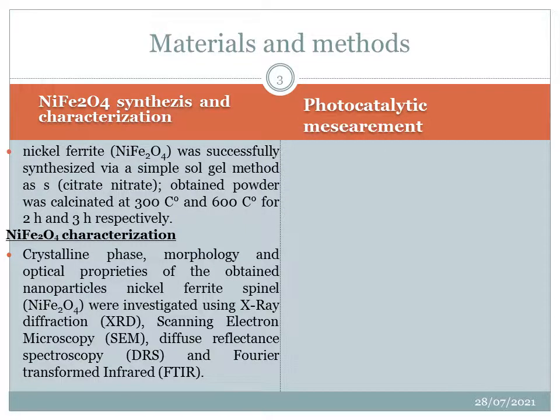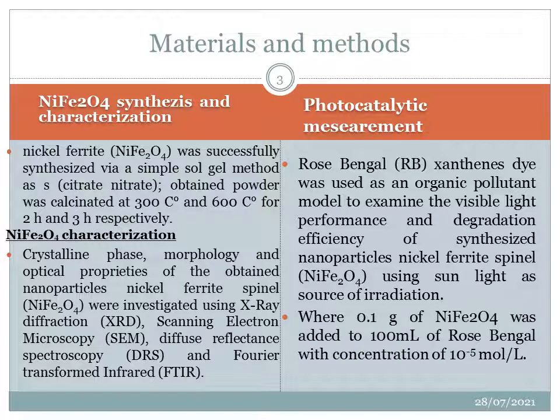For the photocatalytic measurement, the rose Bengal xanthene dye was used as an organic pollutant model to examine the visible light performance and the degradation efficiency of the synthesized nanoparticle nickel ferrite spinel, using sunlight as a source of irradiation, where 0.1 grams of the synthesized nickel ferrite was added to 100 milliliters of rose Bengal with a concentration of 10 to the power minus 5 moles per liter.